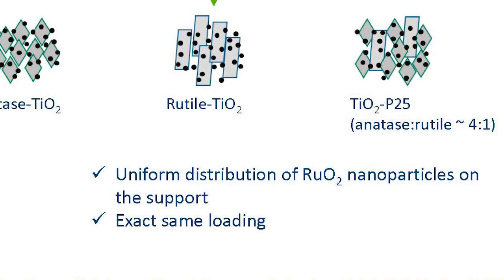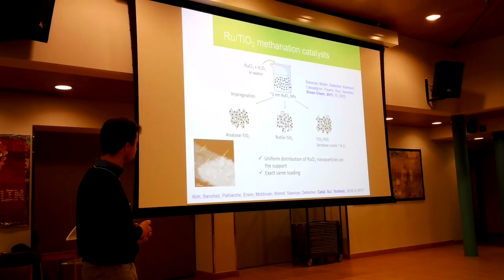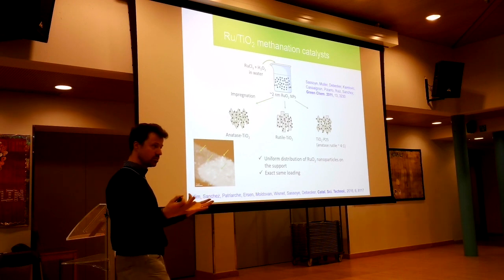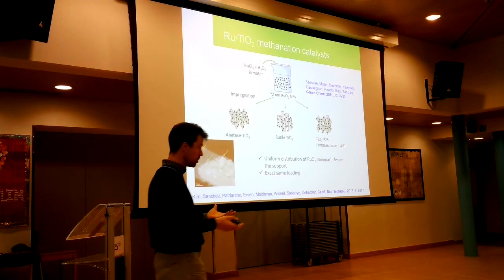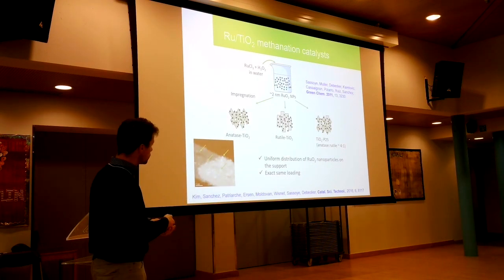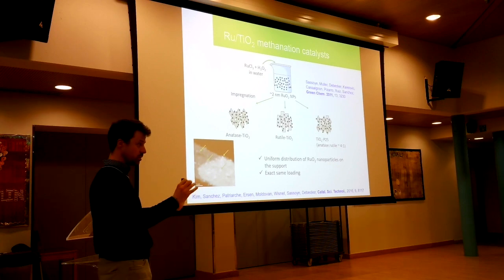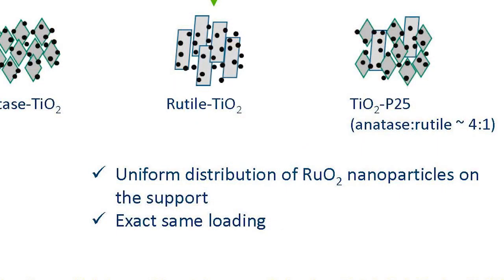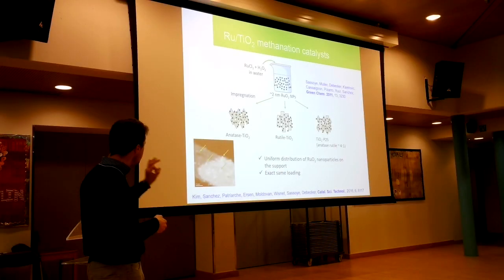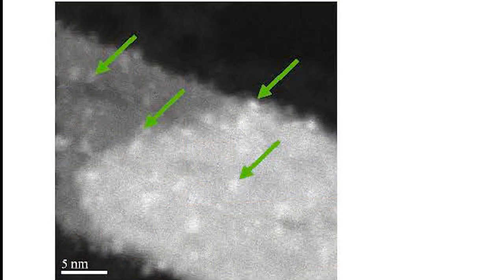So what we did is to prepare dispersed nanoparticles onto those titania. Thanks to this technique here, we could have a uniform distribution of all those ruthenia nanoparticles on top of those supports. And we targeted, of course, this exact same loading. So what we wanted to see is the role of the support itself. So you can see by electron microscopy very tiny ruthenium nanoparticles dispersed everywhere. So we were quite happy with this model system to start.